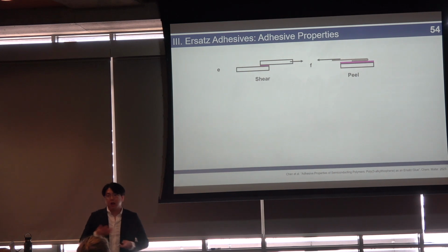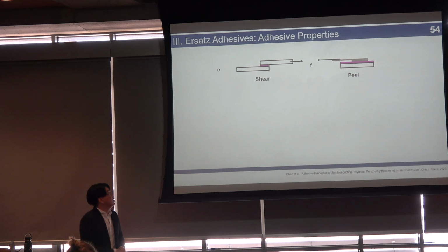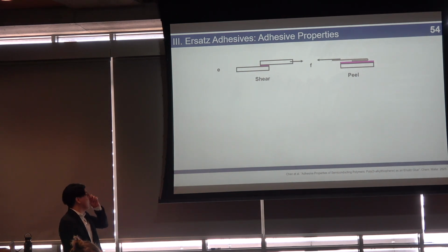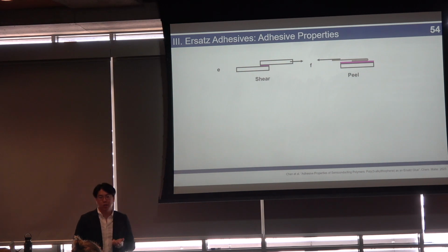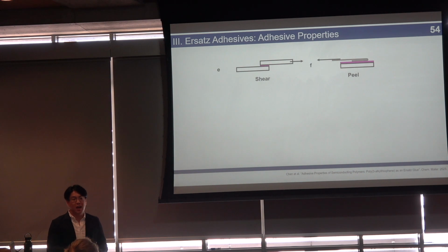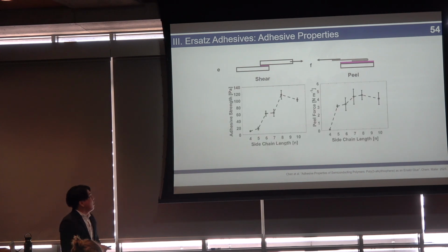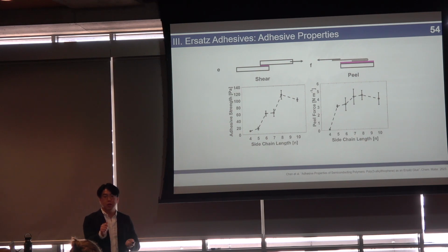So we can start to characterize the adhesive properties. Now we can do a couple different tests. First and foremost, we can do a shear test. In a shear test, we basically sandwiched these polymer films between two glass slides, and we pulled it apart. We also did peel tests, in which we put on a piece of tape and just ripped it off and saw how much force it required.